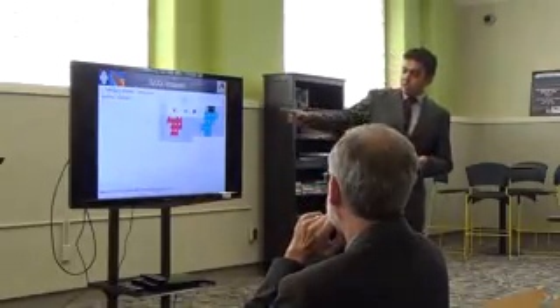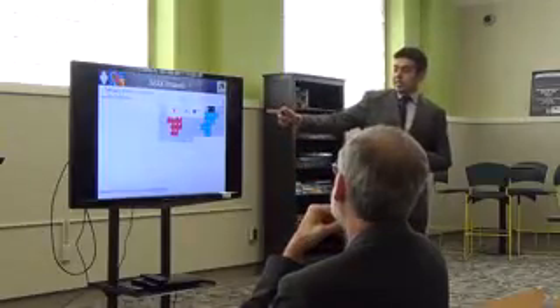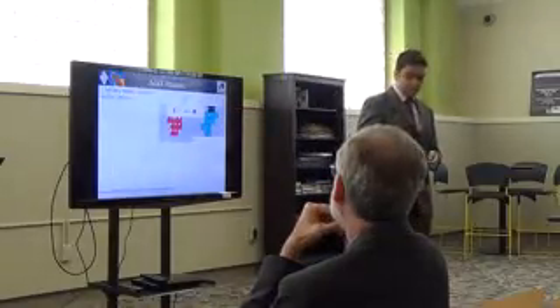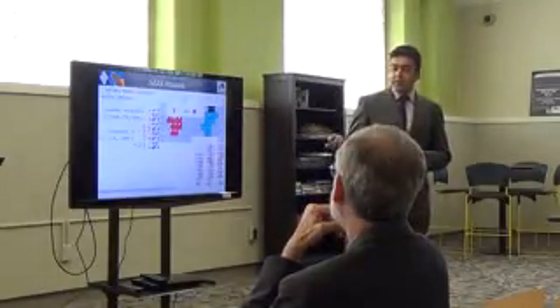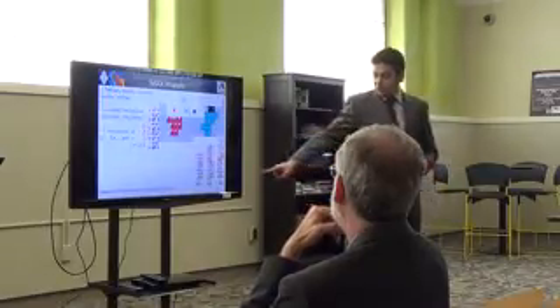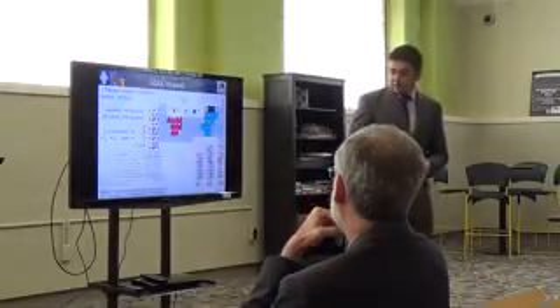And for MAX phase, the M stands for an early transition metal, any of those red highlighted, titanium, any of those. A stands for an A group element, any of those blue highlighted. And X stands for carbon or nitrogen. And they can have the chemistry M(n+1)AX(n). So you can have different structures, 211, 312, or 413. Here are some examples. There are more than 60 different MAX phases.